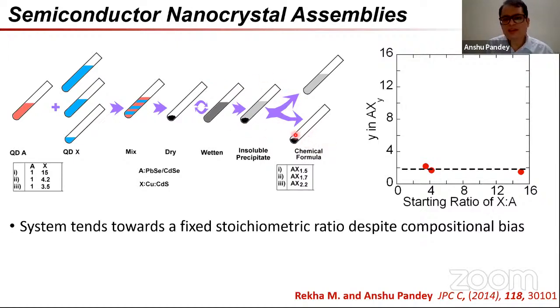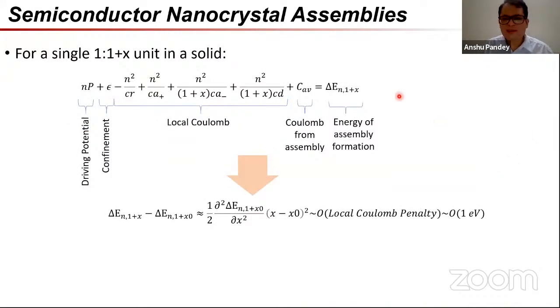Eventually, we get a solid, but the solid, regardless of what bias I put in the composition initially, always has the same final stoichiometry. Around 1.8 average, you see that there's a slight deviation, but given the bias which I'm providing, it's not at all reflective of that. The system has this tendency to tend to a fixed stoichiometric ratio, despite having strong compositional bias to not.